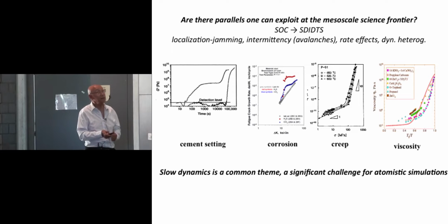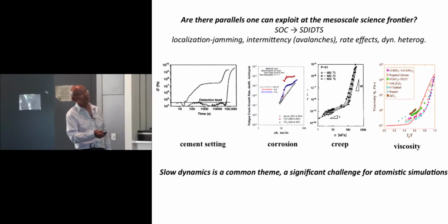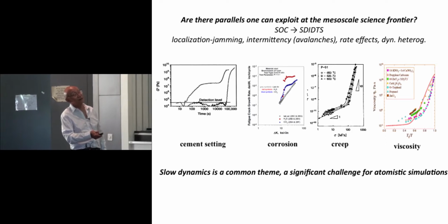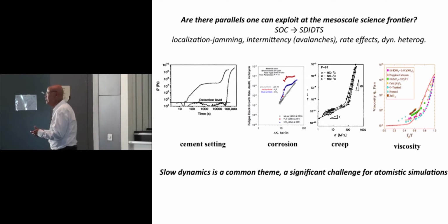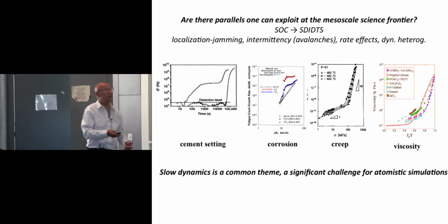And that's what we mean when you have something like the viscosity, which goes from this behavior and all of a sudden shoots up. That suggests very simply that there's a change in the mechanism. For example, if I were a transport person, I would say the change in mechanism is going from continuous collision, as we know from hydrodynamics, as you would have in a liquid, to hopping over barriers, or in the case of stress, localization.